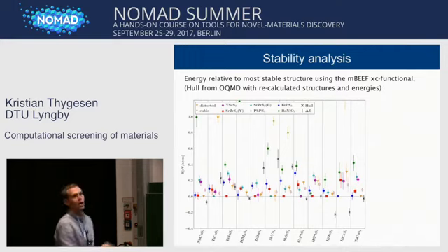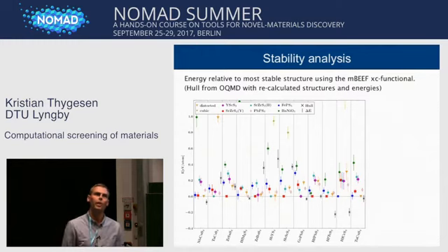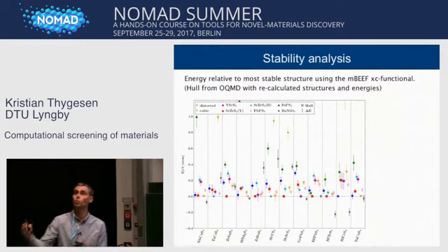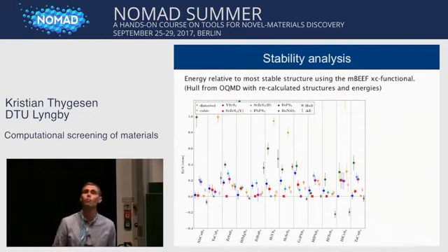You can see there is an error bar in the DFT calculations. And Mikkel will talk more about how to make this error bar in DFT calculations, but I just want to say that these calculations are done with the so-called BEEF functionals. And the BEEF functional works with an ensemble of enhancement factors for GGA functionals. And the width of that ensemble of enhancement factors has been determined by comparing the result of DFT calculations to experiments, right? To known experimental structures. So this error bar here says something about the error coming from the GGA approximation.